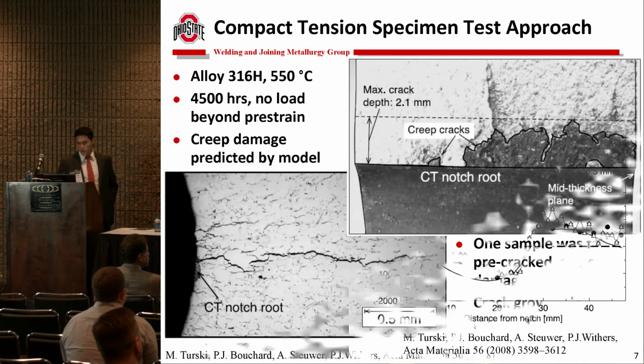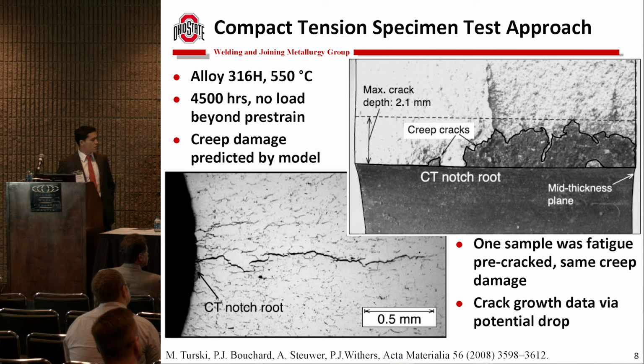So results from this initial work in alloy 316H, this testing was done at 550 C for about 4,500 hours, and these authors were actually able to predict the creep damage with some additional modeling they did. But I just want to focus on the microstructures here. This is half of the thickness of the sample, so this is the mid-thickness plane. And you can see that for a pretty consistent portion beyond a quarter of the thickness here, which would extend another quarter to be over half the thickness of the sample, there's pretty consistent crack depth.